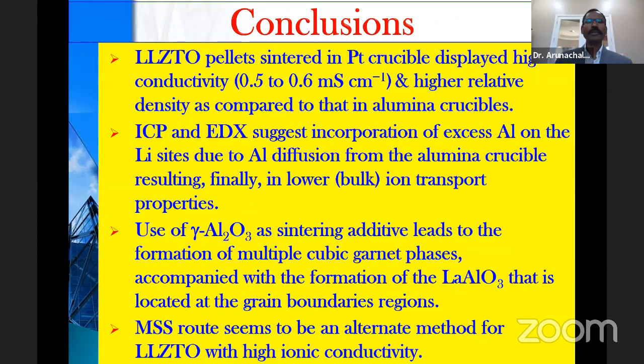So coming to an end, we were able to at least get reproducible pellets with relatively higher density, and also the conductivity is all the way up to 0.6 millisiemens per centimeter using 2 different methods, molten salt and also the solid-state reaction. The molten salt method is a relatively simple method, but I don't know how easy it is to scale up, because there are steps which are conducted in a controlled manner to wash the salt, lithium and potassium chloride salt.